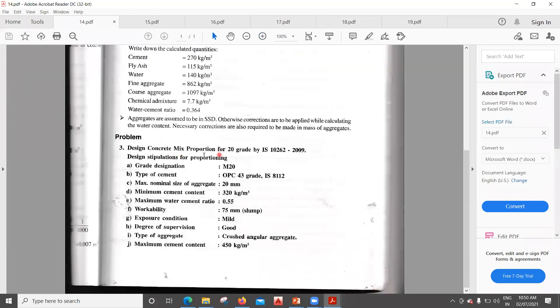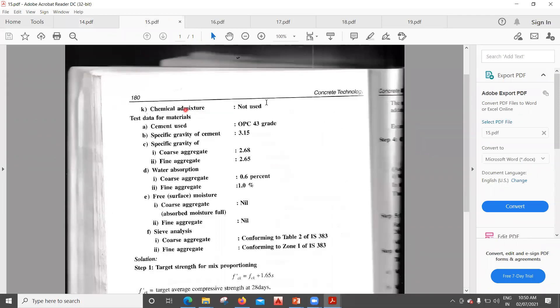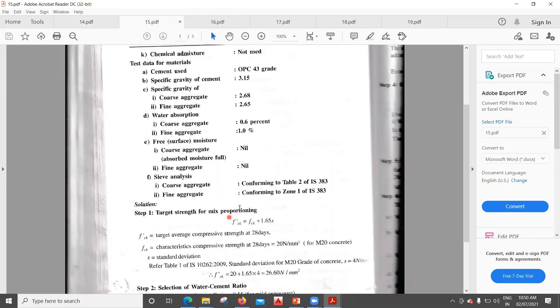The question asks us to design a concrete mix proportion for M20 grade concrete. Type of cement is OPC 43 grade, maximum nominal size is 20 mm, minimum cement content is 320 kg/m³, maximum water-cement ratio is 0.55, workability is 75 mm slump, exposure condition is mild, degree of supervision is good, type of aggregate is crushed angular, and maximum cement content is 450 kg/m³, and chemical admixture is not used.